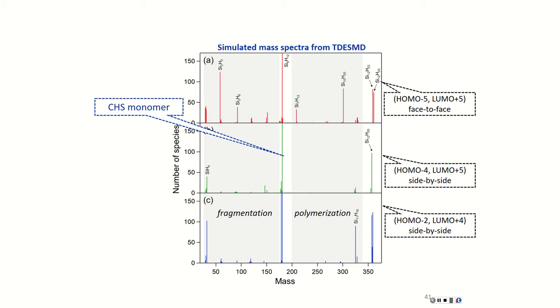And there is an interesting observation that as long as we change wavelengths of initial excitation or original orientation of the precursors, one can observe both fragmentation onto smaller, like silane gas with only single silicon, or polymerization with heavier fragments. But by changing wavelengths of excitation, one can control and enhance one pathway against another one.